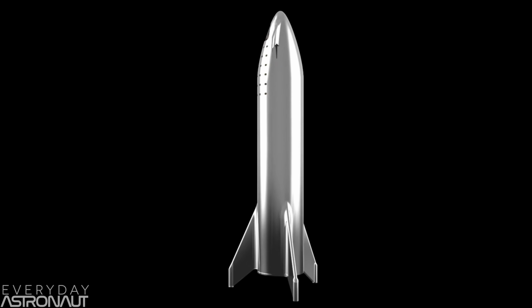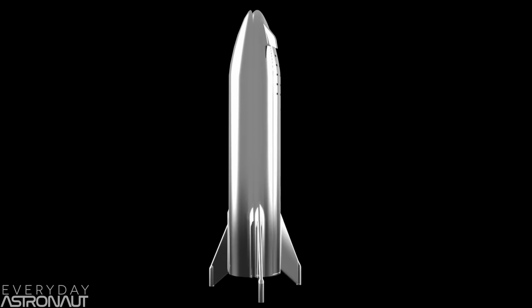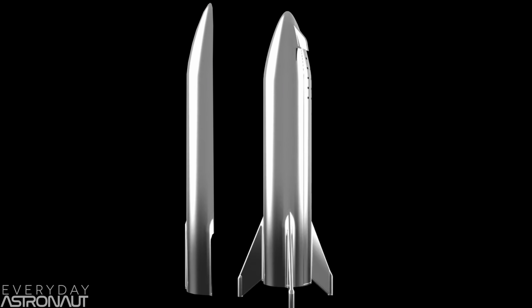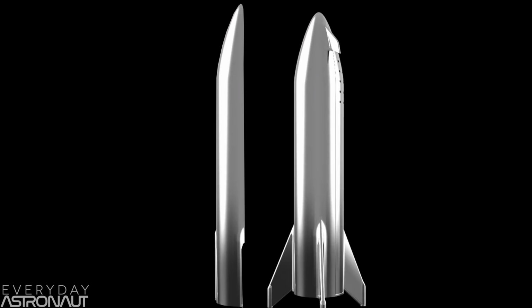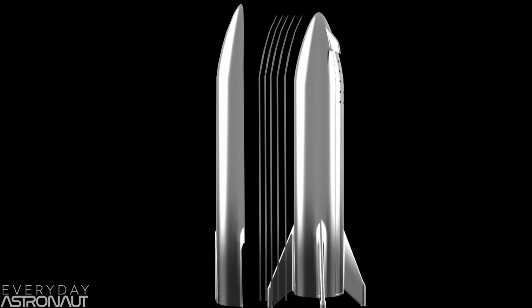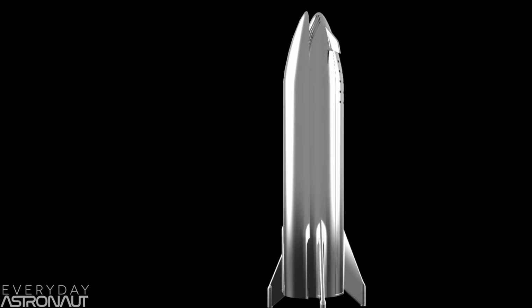Basically, on the belly of Starship will be another layer of stainless steel, but this time they'll use 310S stainless steel, which can handle a higher peak temperature. Then between those delicious layers of the stainless steel sandwich will be some stringers which will actually flow liquid methane when being actively cooled. Now, I know this sounds crazy, like what if that fails? I mean, it's your heat shield.